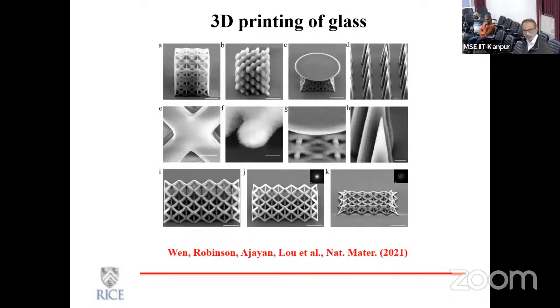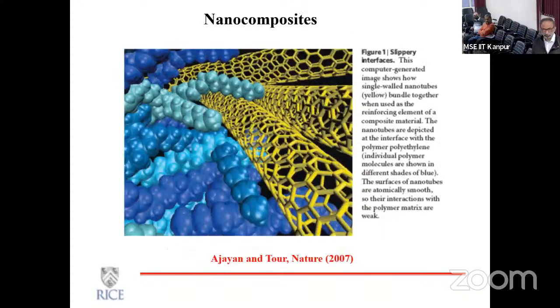And here is actually a very recent example that we did. Again, it's not simple 3D printing. It's this 2-photon polymerization approach where you can get very, very fine features for 3D printing. In fact, we were able to print glass. And in fact, we were able to print quartz at very, very fine scales. So again, innovations, creativity, improvement in instrumentation, facilities, all these things add value to what we can do and how we can change the world.